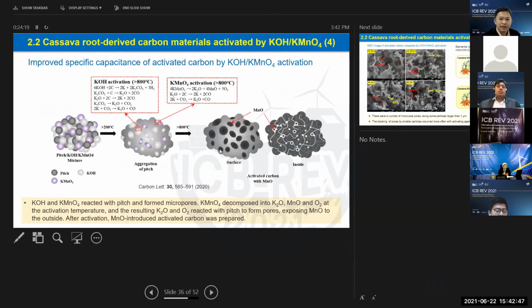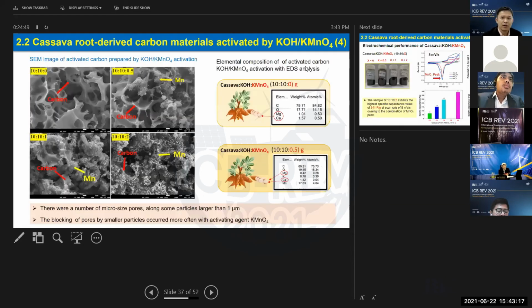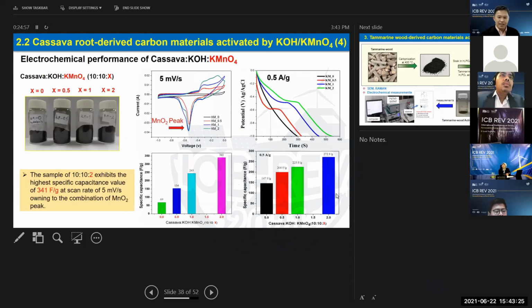And we also try to increase this value by introducing some potassium permanganate to the system, because there is some paper reporting that when they mix potassium hydroxide and also potassium permanganate to activate the carbon, they get better electrochemical performance. So we follow that concept, and we get a very good result, as I will show you later. And here you can see when we introduce the potassium permanganate to the system, the value of the specific capacitance increased. For example, this one from 69 farad per gram can be higher, up to 341.